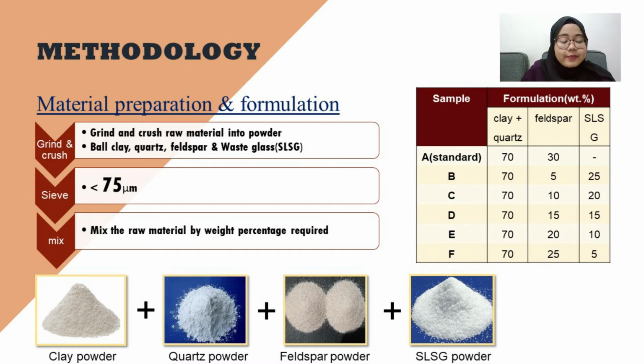The procedure starts with material preparation and formulations. The materials, which are clay, quartz, feldspar and soda lime silicate, were ground and crushed into powder by using a planetary ball mill machine. Then the materials were sieved separately to a size of 75 microns. Next, the materials were mixed according to the formulation as in the table shown.